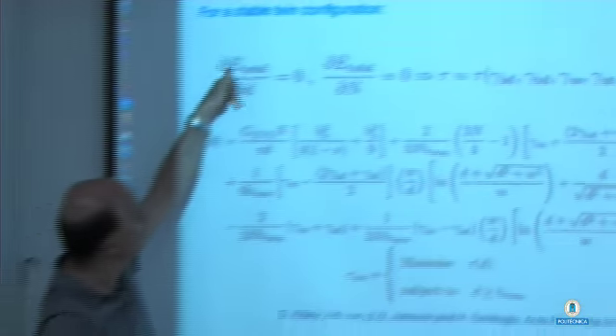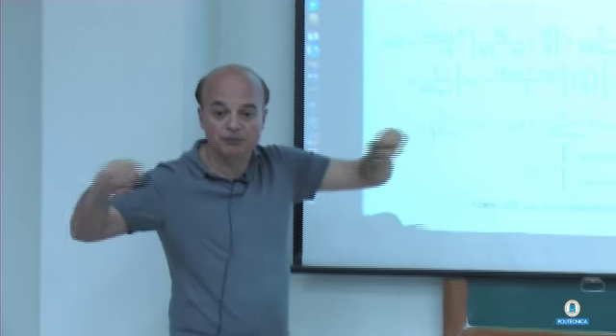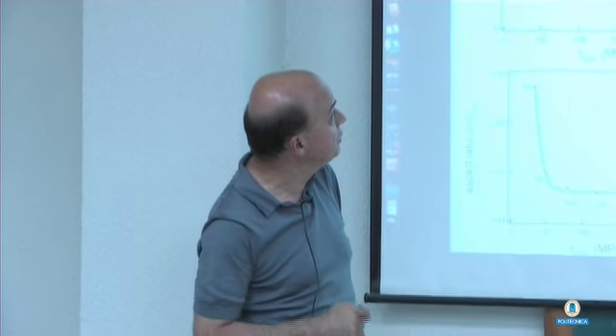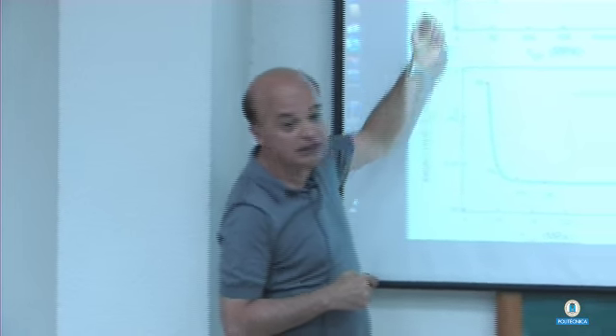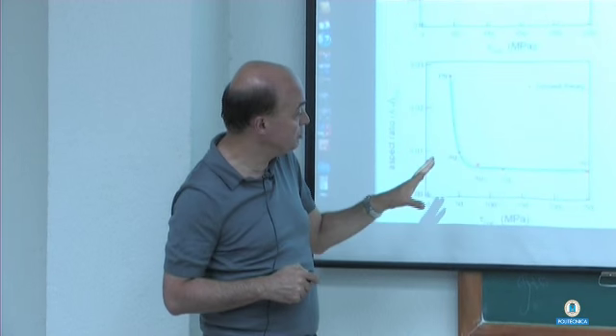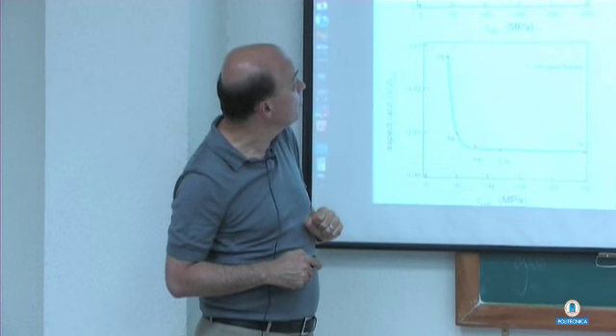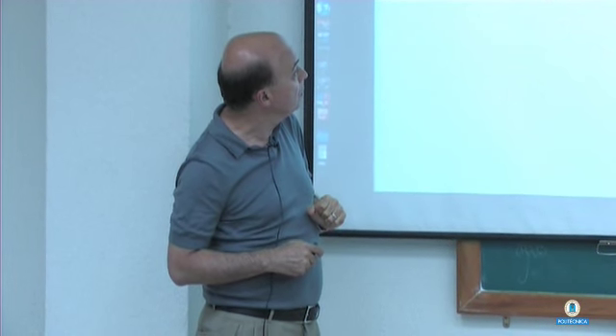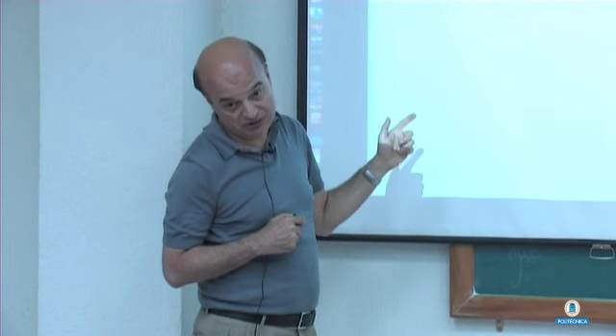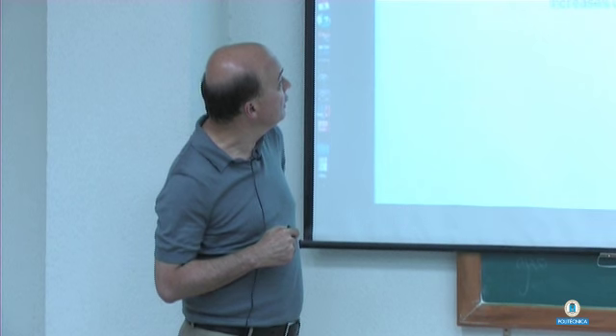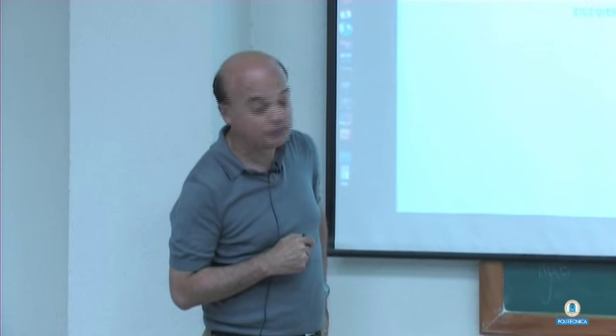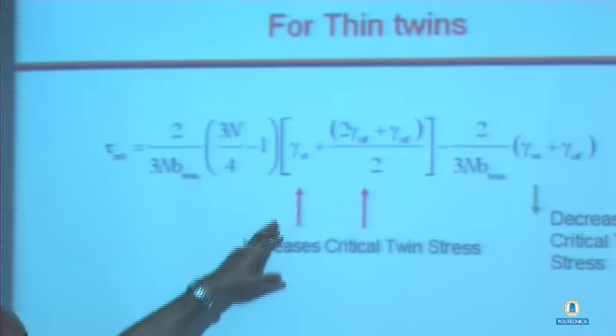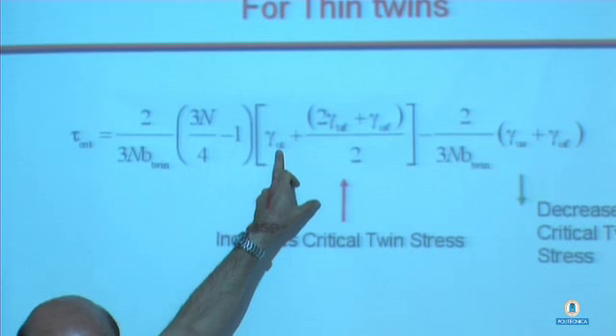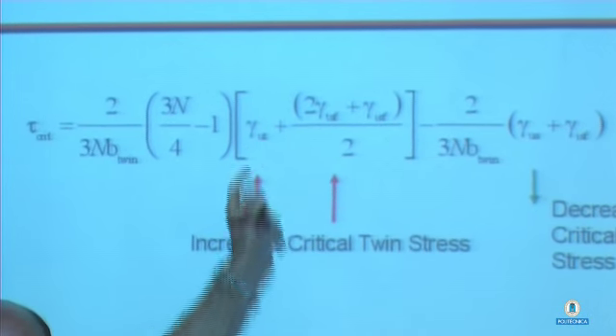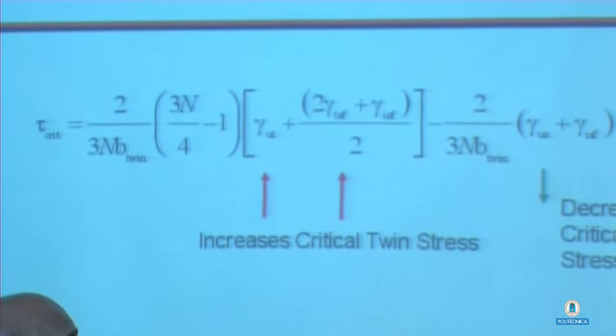We can certainly determine from this calculation the equilibrium width of the twin as well. And for nickel versus lead, that D is different based on our calculation. But most importantly, we can simplify this complicated looking expression and get the following result. The critical stress for twinning is equal to a term which has gamma UT, the unstable twin energy, and if that goes up, the twinning stress will go up.